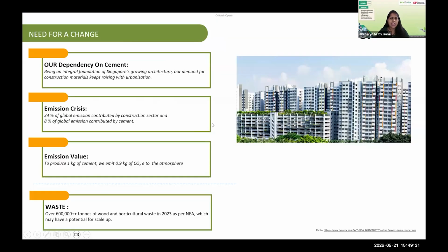So looking into that, if we look around us with the constant urbanization, there is no doubt cement is being used all around us, or at least it's around us everywhere, right? Much has been said already on it contributing 8% of global emissions, and a sector which is actually contributing up to 34%, right? Keeping these numbers high, we can do the math to say that when 1 kg of cement is produced, 0.9 kgs of CO2 is emitted. When I started in this industry, the values were much higher than this, and it has really significantly come down, yet there is need to do much more.